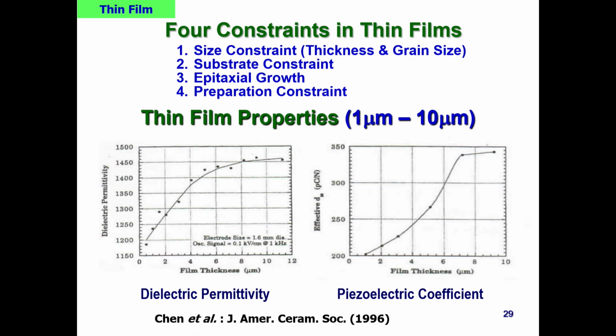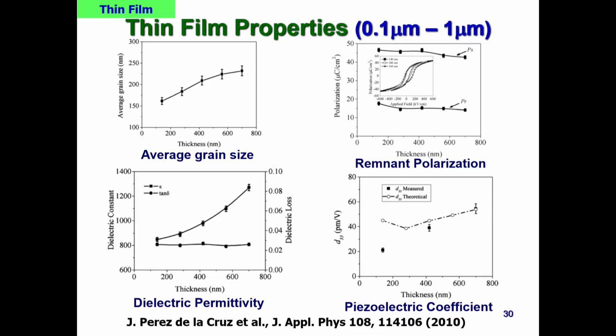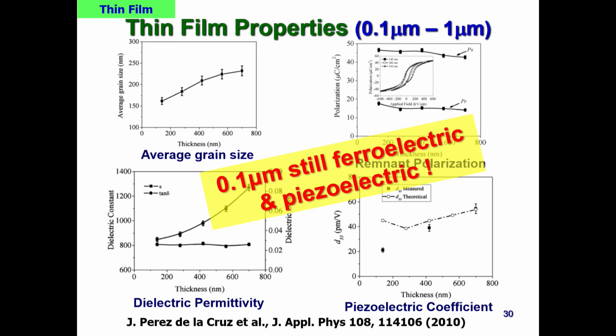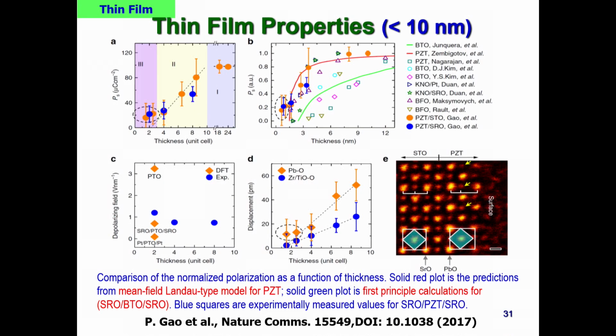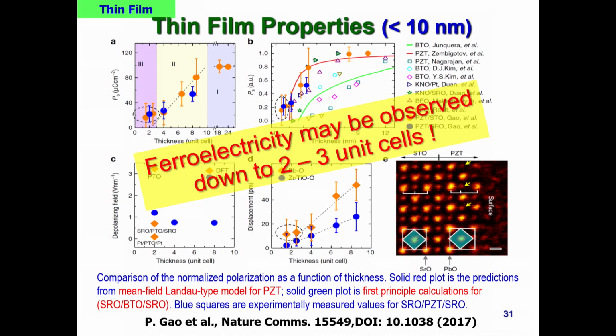So in the 1990s, in the 1 micrometer to 10 micrometer range, with reducing thickness, the dielectric permittivity, or constant, decreases. After getting into 2010, in the 0.1 micrometer to 1 micrometer range, the dielectric permittivity again gradually decays, okay? So at 0.1 micrometer, ferroelectricity and piezoelectricity still exist. So how thin is the critical thickness? Therefore, in the most recent papers, this is intriguing. Less than 10 nanometers, a couple of unit cells, still creates some ferroelectricity-like behavior. So believe it or not, this is the waiting period: how thin can it be and still create real ferroelectricity. Ferroelectricity may be observed down to 2 to 3 unit cells.